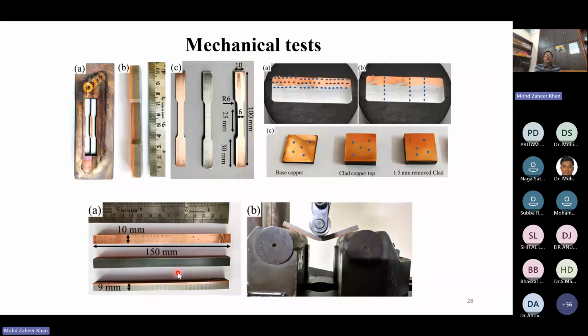In one case, the bend was carried out such that, as you can see in this figure, the clad layer is at the bottom, the substrate layer is on the top, a plunger is kept, and a U bend test was carried out, so that the maximum deformation is there in the cladded material, less deformation is there in the substrate material. Next set of bending was carried out, where the substrate material was at the bottom, the clad layer was at the top, and when the plunger was moving down, there was maximum deformation in the substrate layer and less deformation in the clad layer. In fact, the clad layer was subjected to compression. And the third test was that this specimen was kept perpendicular to this, and it was deformed so that the clad layer and the substrate were deforming together.